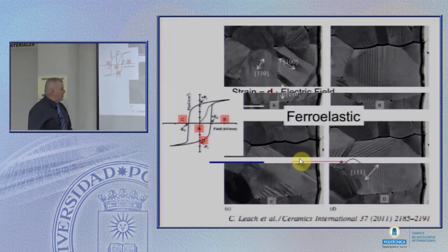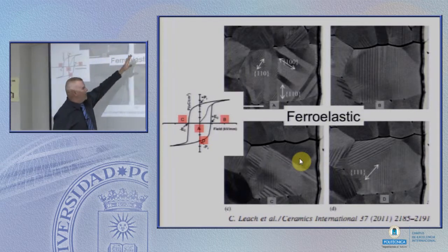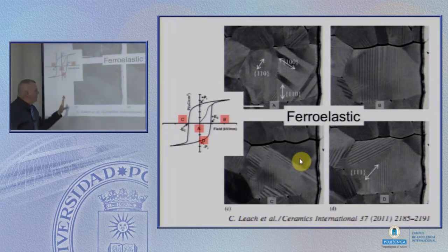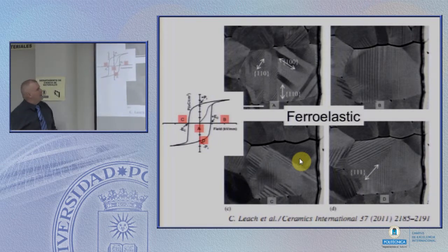The materials that we work on have two characteristics. This is just a set of images documenting, and there are not many examples where you can see these, but documenting the fact that what we have inside of an individual crystal in these materials are domains. So I showed earlier, for example, for tetragonal, and I discussed it in terms of having the C-axis perhaps being up in that case because I showed the polarization. It turns out an individual unit cell has a choice of its C-axis being up, horizontal, or going in.